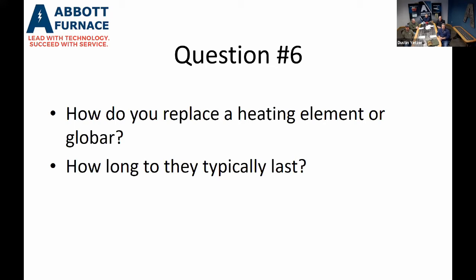So when you replace heating elements in a preheat, you can do one at a time. If you have one bad heating element, you can replace it if it broke, or the support tube broke and cracked your heating element, and you don't have power going through it. You can replace the one without any degradation to anything else in that zone.